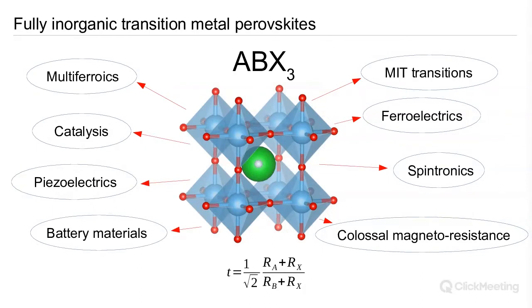And then what we see is a well-characterized set of octahedral tilts and rotations at that onset in order to accommodate the smaller cation at the A site. And the tolerance factor can actually go quite a way below 1 and still remain a stable phase. And one of the appealing things about this framework is that it lends itself to kind of a fundamental